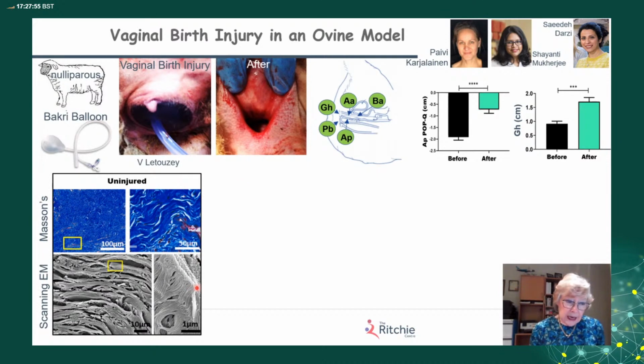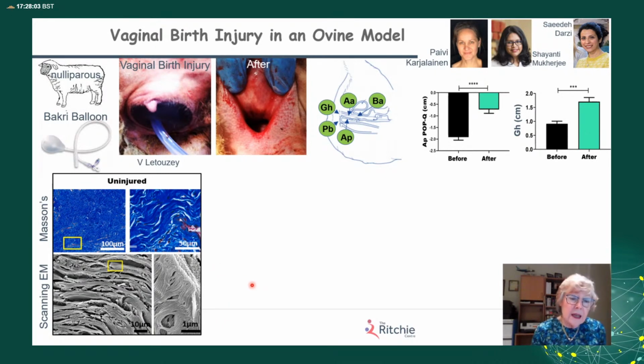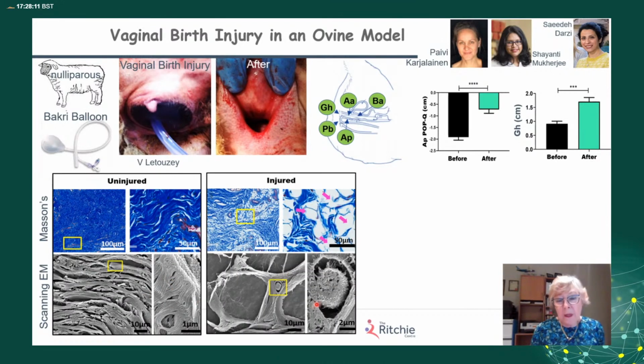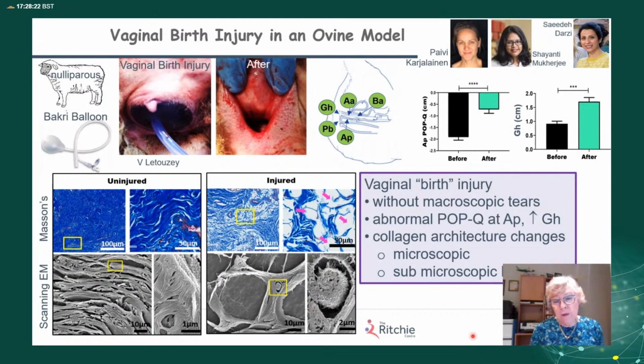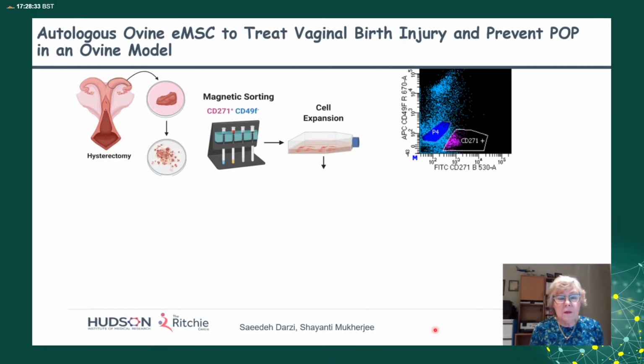We then, 60 days later, when we harvested the animals, we looked microscopically at the tissue. It was normal macroscopically, basically, and you can see what the collagen looks like at Masson's trichrome and under the electron microscope. Notice the fibrillar structure. In the injured animals, which still look quite normal macroscopically, you can see that the collagen architecture is not normal microscopically or at the submicroscopic level. So our birth injury model shows some abnormal POP-Qs, and the collagen architecture is altered at the microscopic level.